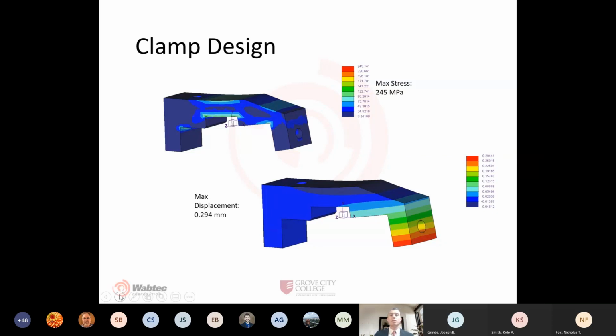Performing finite element analysis on the clamps, we saw that the final clamp geometry saw a maximum stress of only about 245 megapascals. This was also seen in sharp modeled corners that don't actually exist when the part is manufactured. So the actual maximum stress may be slightly smaller. Regardless, the stress is less than half of the ultimate strength of 4140 steel, which means that the clamps will stand up to both the initial loading and any fatigue stresses.